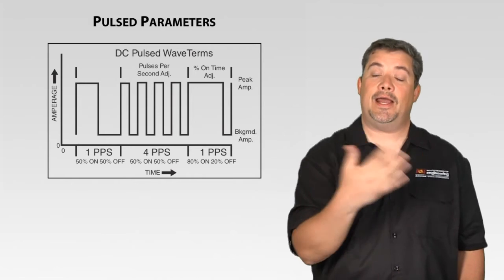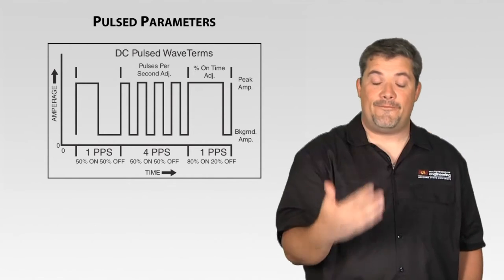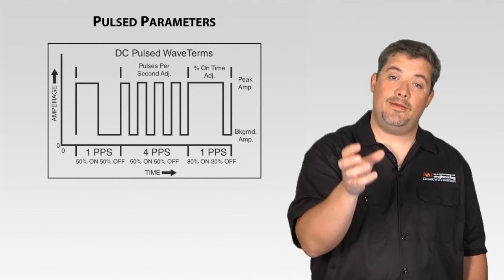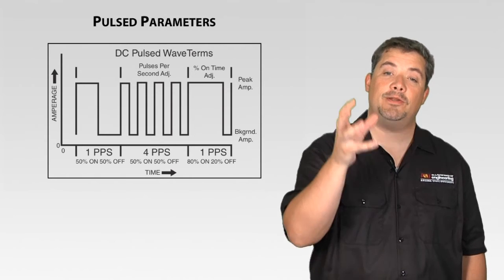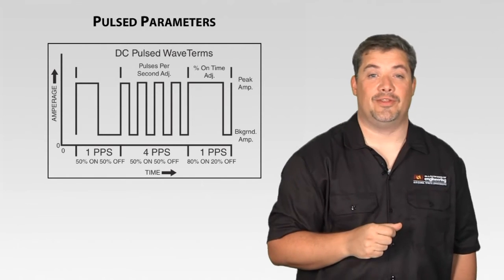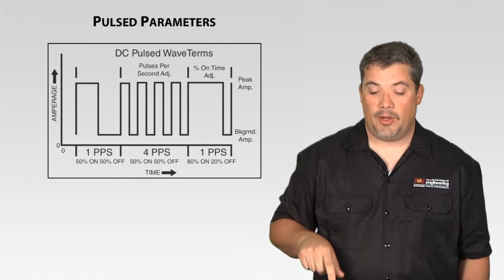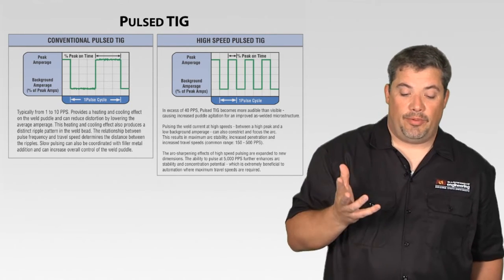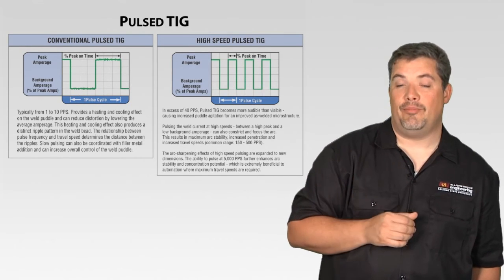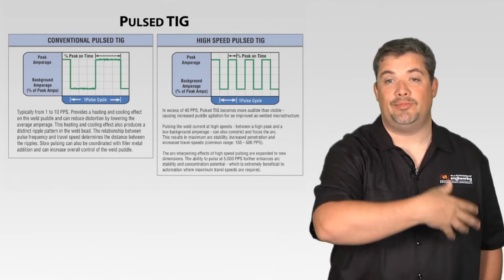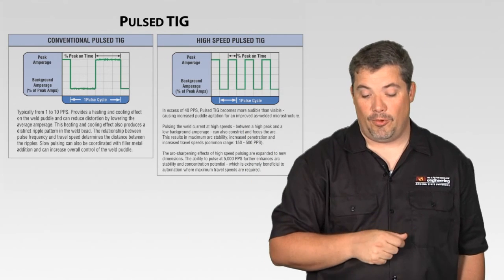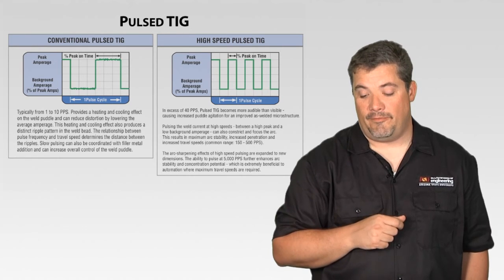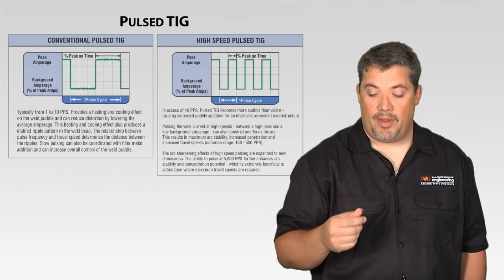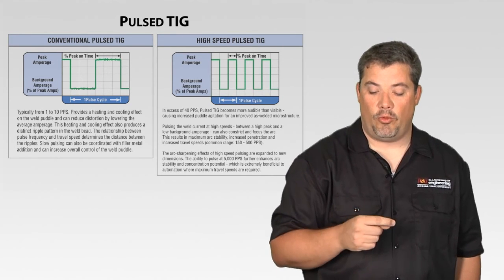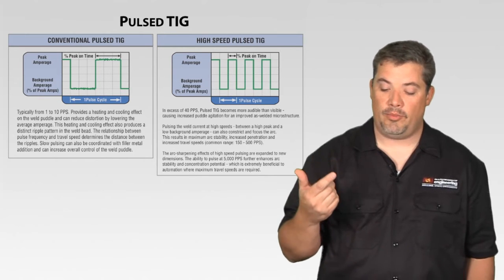Again, pulse, kind of like all that AC stuff, affects the narrowness of that bead, the shape of the profile of the penetration, getting rid of sluggish stuff off of the surface. Pretty neat stuff. So conventional pulse TIG, again, typically from 1 to 10 pulses per second on old school machines, but the inverters give me that 0.1 to 5,000 pulses per second. And basically when it becomes more than 40 pulses per second, it's more audible than visible.